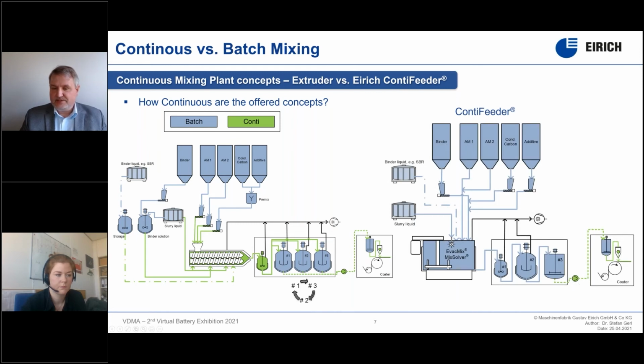Then the final slurry is transferred into degassing tanks and storage tanks, because the degassing cannot take place completely inside of the extruder. And these tanks are batch again. From here, we are then pumping the slurry portion-wise or continuously to the coater, which at the end really operates continuously. This was the reason why we said the EIRICH mixer is capable to run for a very short time. We can refill a tank, and by this we can also supply the coating slurry in exactly the same way as the extrusion system.